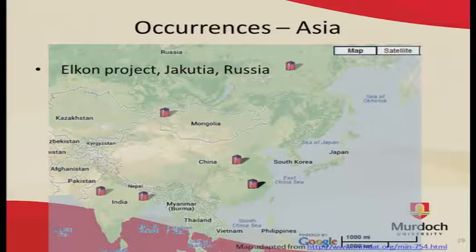Relatively intense conditions were used, with residence times of about a couple of days. That was what was required for adequate recoveries. And there's a fairly large deposit in Siberia that's been known for about 40 years, in which brannerite is the main uranium mineral.